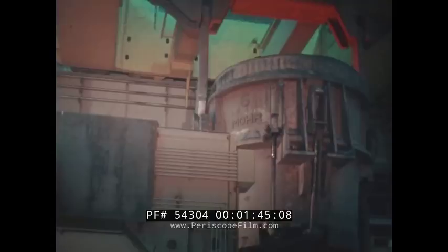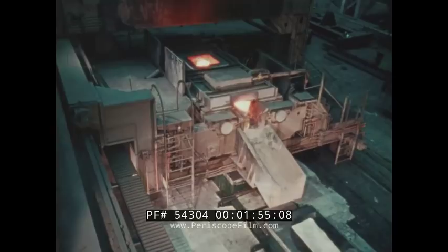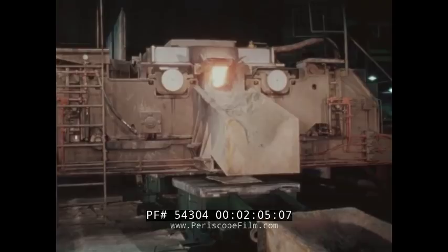The ladle rises smoothly up toward the giant tundish car, which is ready to move into pouring position directly over the two molds. The huge tundish, which serves as a pouring reservoir, encourages the flotation of products of deoxidation and tends to prevent vortexing by the streams pouring into the molds, thus assuring compositional uniformity from the beginning to the end of the heat. The tundish is preheated in preparation for the pour. U.S. Steel's production capacity of strand cast steel exceeds all other producers in the United States.